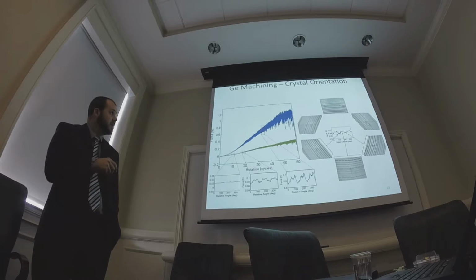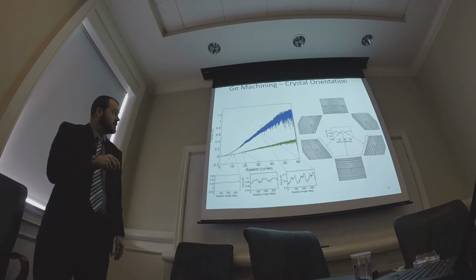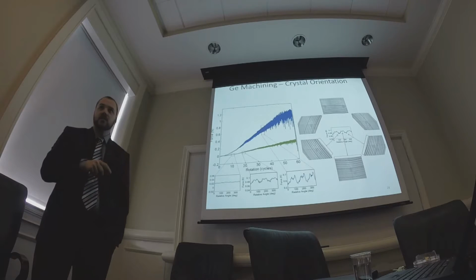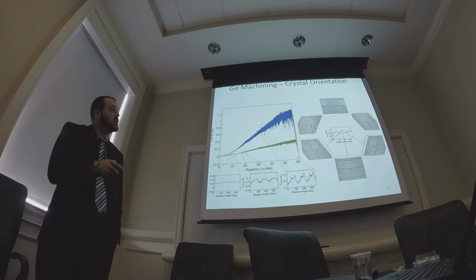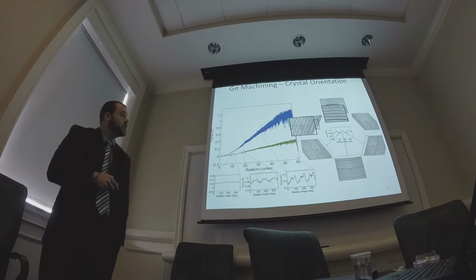We saw that as well, and we wanted to see, do we see that in the force? So here's one of the spiral tests, and if we zoom in on what looks like noisy signal, it's actually this 3 per rev fluctuation in force as we work our way around the surface. I've put these red lines here to show radially that this and this line are at the same point. We don't see fracture here, here, or here, but we see fracture in most of these along here. If we zoom in on that...